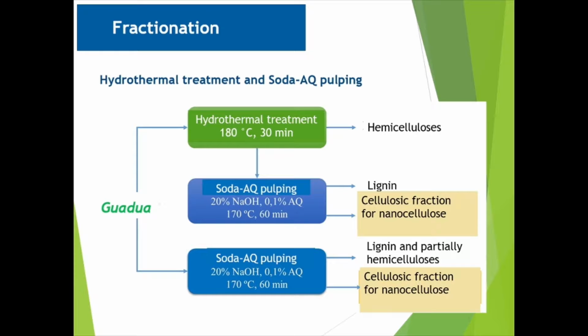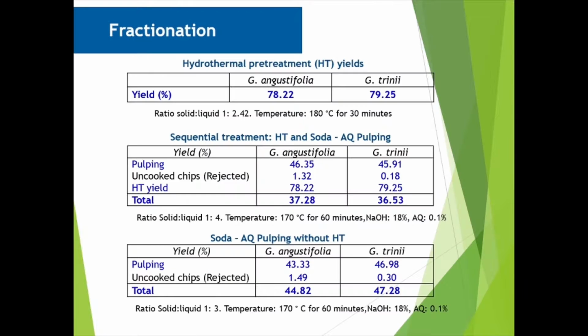A stainless steel digester was used for pulping, which was heated in another small MK-type digester with automatic temperature, speed, and heating ramp controller, using water as fluid. The soda anthraquinone pulping conditions are shown on the slide. In the sequential treatment, the autohydrolysis yield was around 78% for Guadua angustifolia and 79% for Guadua trinii. The total pulping yield was similar for both species, which was around 37%. In the samples without hydrothermal pretreatment, the pulping yield was significantly lower for Guadua angustifolia than Guadua trinii, that is to say almost 45% and 47% respectively.